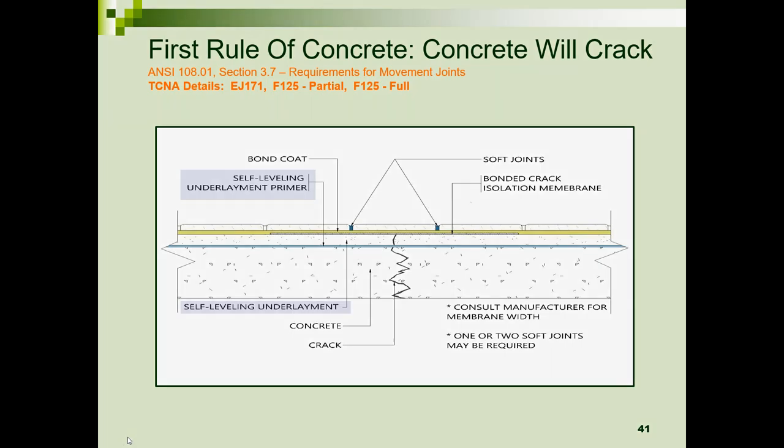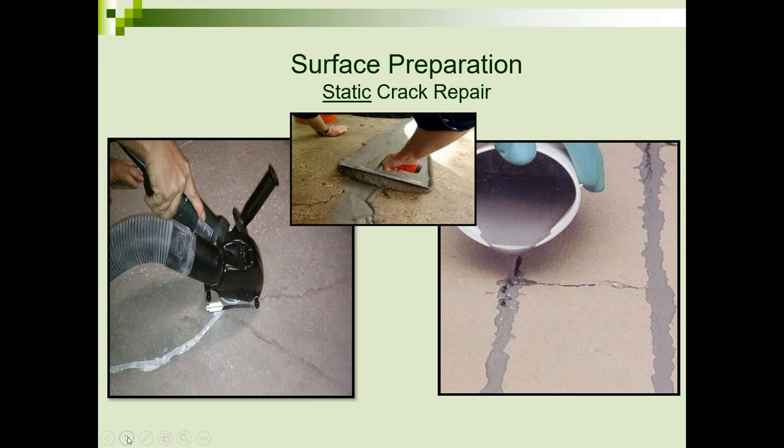Next slide, couple clicks, Bill. Click again. And as far as static crack repair, you have a couple methods to choose from. You could route out the crack as we see on the left and pour in or apply a neat epoxy, 100% solids, or you can take that same epoxy, add a clean graded sand, and create a trowel mix for filling wider cracks or joints.